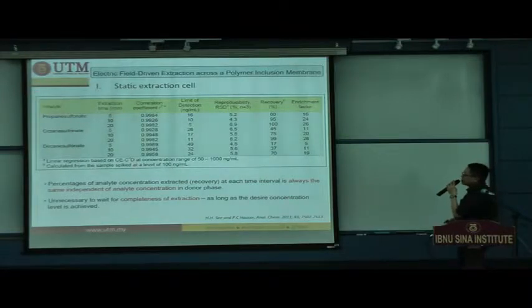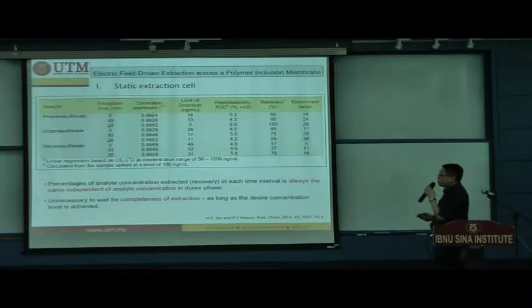Surprisingly, the percentage of analyte extracted, what we know as the recovery, is actually always the same, independent of the analyte concentration in the donor phase. Which means, for example, if you perform a 5-minute extraction with different ranges of concentration in the sample solutions, you always receive a recovery of 60%. You won't see a phenomenon whereby if you put in more, more analyte will migrate. No. And since the recovery is always consistent, this is extremely good if you would like to develop an extraction method.